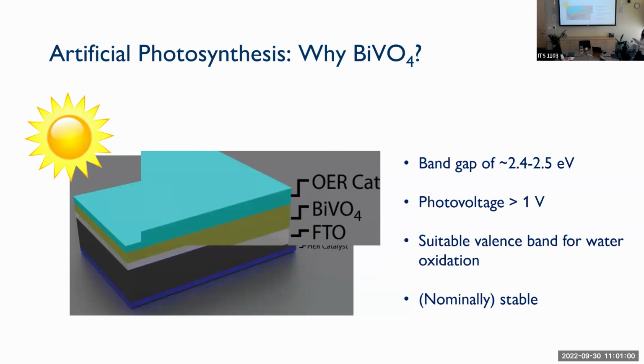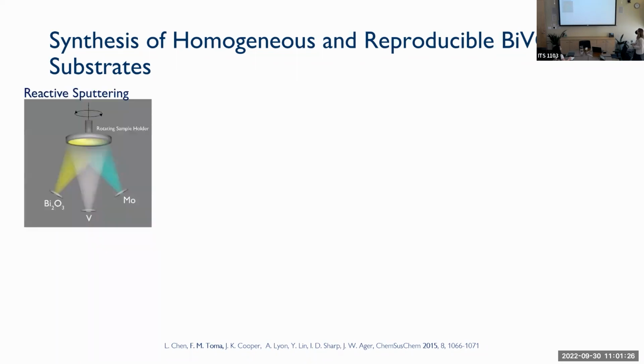And when I started studying this material, since it's a metal oxide, it was known to be stable in oxidation conditions. I say known to be stable because I will actually show you that it's not stable if you want to make a system that can work for several years. But again, because the first and foremost focus is on efficiency, I also started down that route, and I said I'm going to make BVO better. And making BVO better for us meant doping bismuth vanadate. I'm calling it BVO, but it's bismuth vanadate. We doped it with molybdenum.